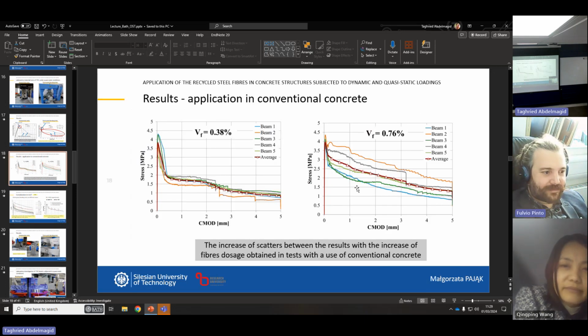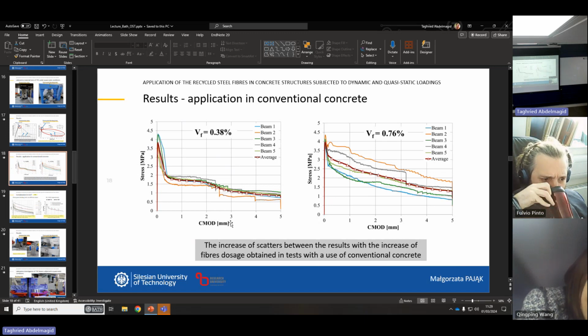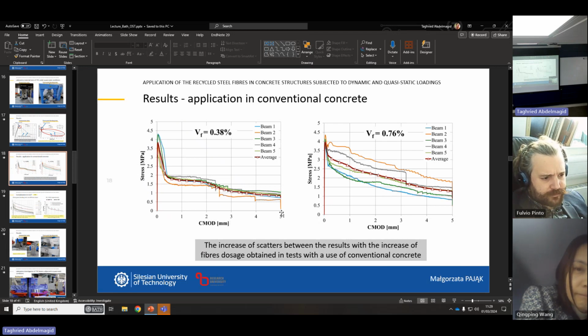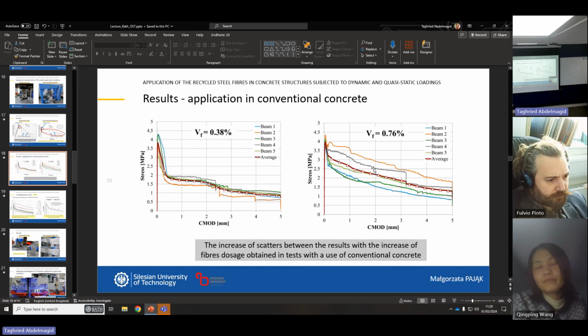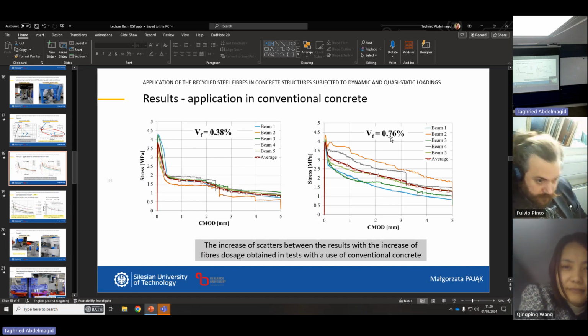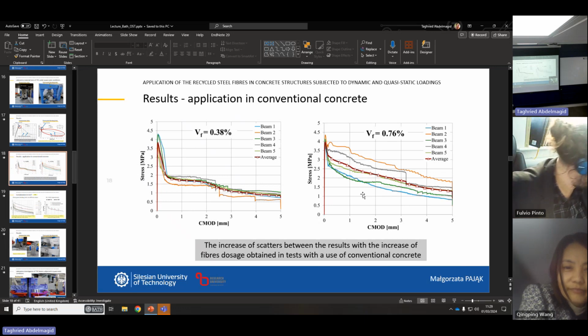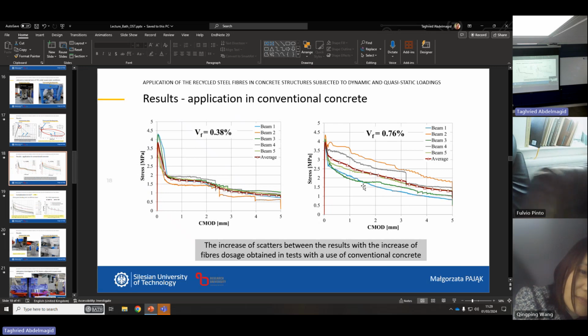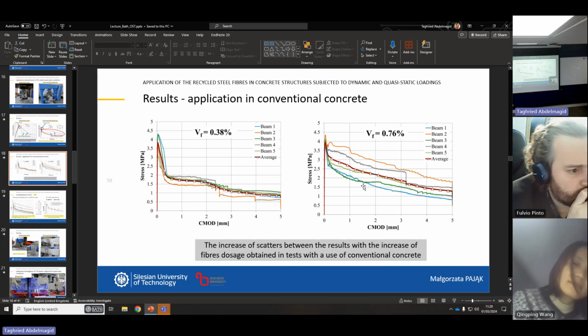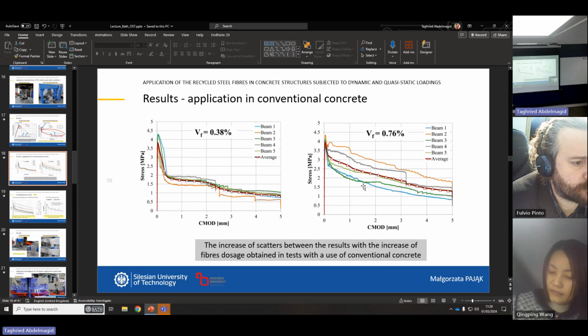So this is what happened in concrete. When it was vibrated in conventional concrete, that's why after this research we started to use only self-compacting concrete. Because for a small amount of fibers there was completely no difference between the results. But when we got more than 0.5, the scatter was pronounced. So I think that it is connected with the vibration of the concrete. For the self-compacting concrete, the results are, let's say, quite okay for a fiber reinforced concrete. But here, the scatter was really pronounced.